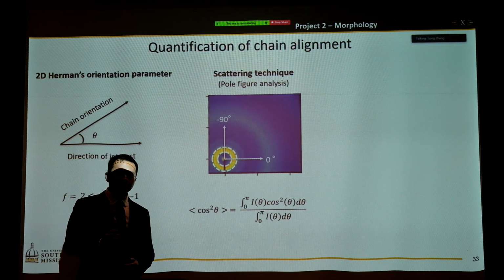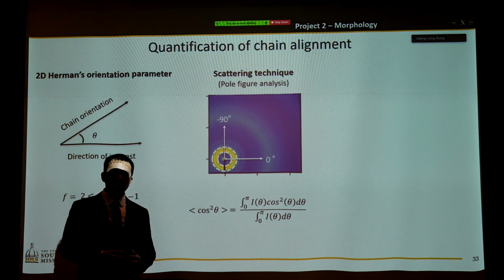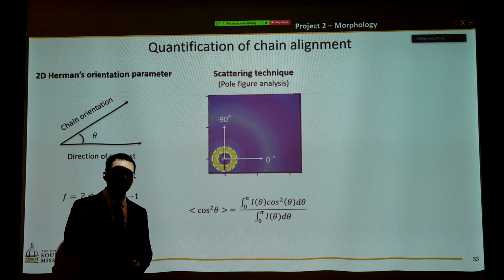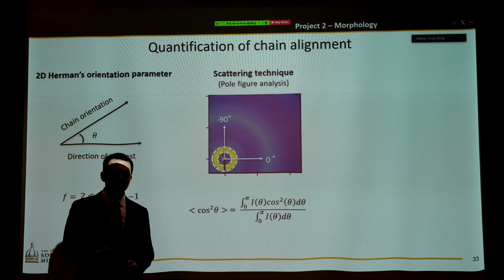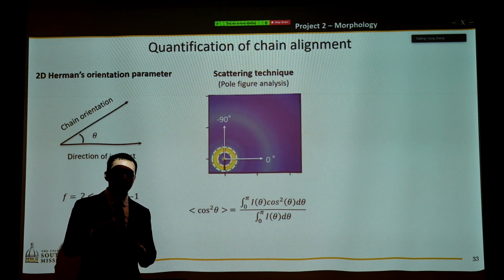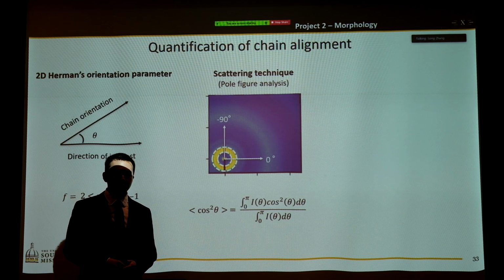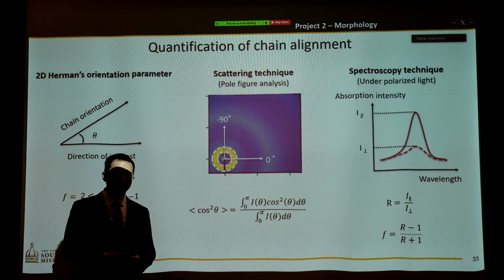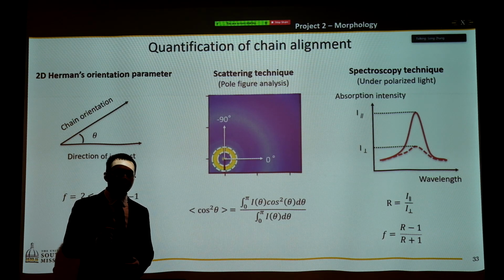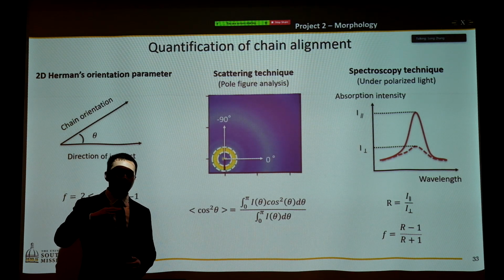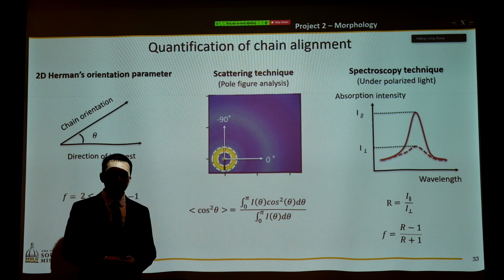Okay, so by using scattering technique, we can do the pole figure analysis on a specific peak, and that is telling us what the anisotropy is like for that peak. And by using spectroscopy technique, we can provide a dichroic ratio from the absorption when the film is parallel versus perpendicular, and obtain this F value using this simple equation.